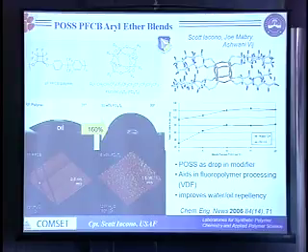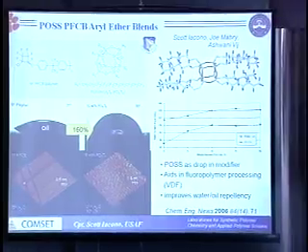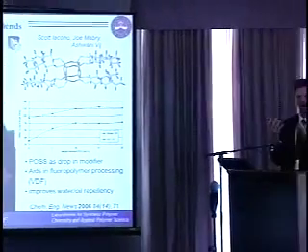They want something that's really going to be resistant to the jet fuel. And you can see why. Here's the AFM image. You get this nice nano roughening, so you get the synergistic effect of the fluorocarbons blooming to the surface, and this POSS material, whether the POSS is actually on the surface or is just bulging the polymer up a little bit, you get this effect.